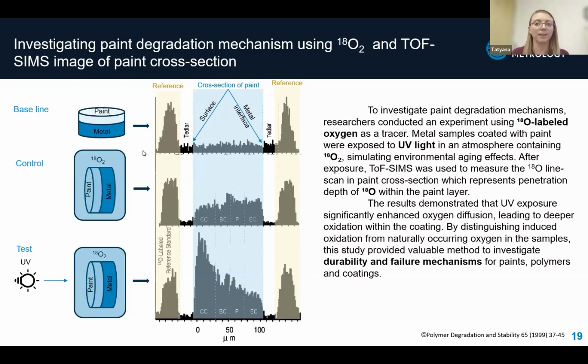Let's start by understanding the experimental design. Baseline sample was kept at normal condition. A control sample was exposed to O18, but not to UV light, and the test sample was exposed to both UV and O18. After exposure, ToF-SIMS was used to measure the O18 image of the paint cross-section, like on the previous slide. The figures represent a line scan of penetration of O18 within the paint layer.